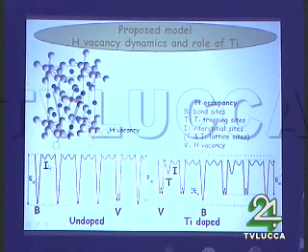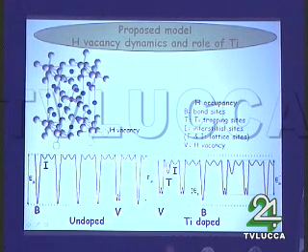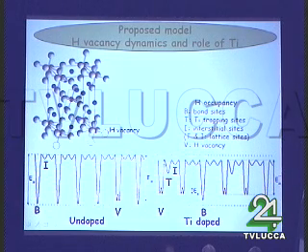The presence of titanium modifies both the site energy for hydrogen and the saddle point energy, resulting in the decrease of the barrier height necessary for a hydrogen to leave the bond.